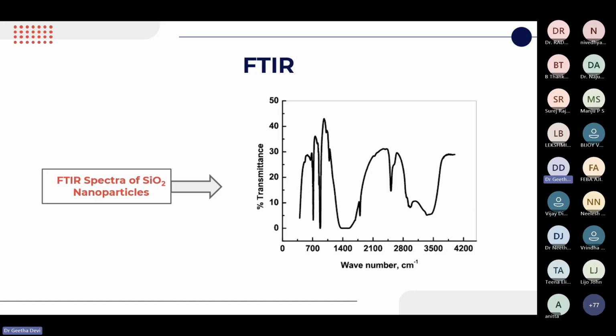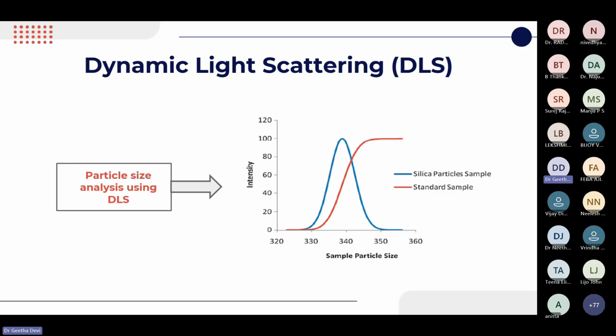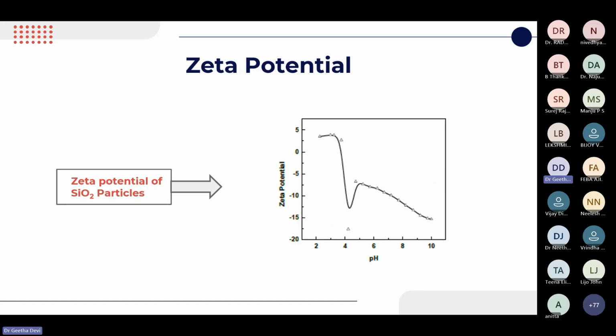And the Fourier transform infrared spectroscopy shown here, it has got many representative peaks which represents the different functional groups present on the surface of nanoparticle. This is the dynamic light scattering DLS analysis. You can see that one single peak represents the particles are almost the same size range, that is 300 to 350 nanometer, and the average size is almost 340 nanometer, which confirms the size of the nanoparticle. This is the zeta potential measurement of the nanoparticles.